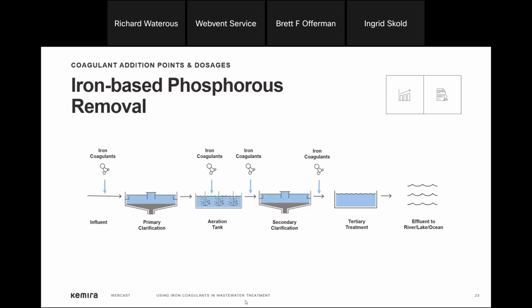Determining the coagulant dosage level begins by establishing the soluble phosphate level in the wastewater to be removed. Phosphorus in wastewater is separated into three main fractions: inorganic orthophosphate, inorganic polyphosphate, and organically bound phosphorus. Chemical phosphorus removal is based on two different mechanisms. Chemical precipitation of phosphorus includes converting the dissolved inorganic phosphorus compounds, mainly phosphates, to a low solubility metal phosphate through the use of iron-based metal salts.